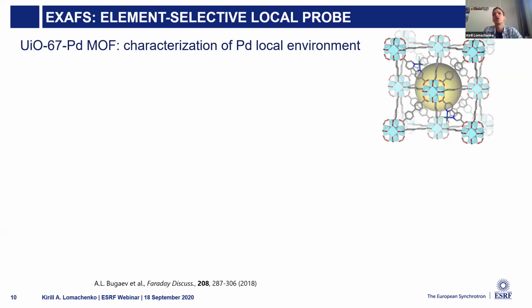The question here was whether the structure of this linker molecule with palladium is maintained after the synthesis of the MOF has been done. The linker synthesis was done by pre-making the linker, so the linker was ready before the synthesis, and then we synthesized the MOF. We want to know whether the linker molecule is still intact, whether the local environment of palladium is still the same.